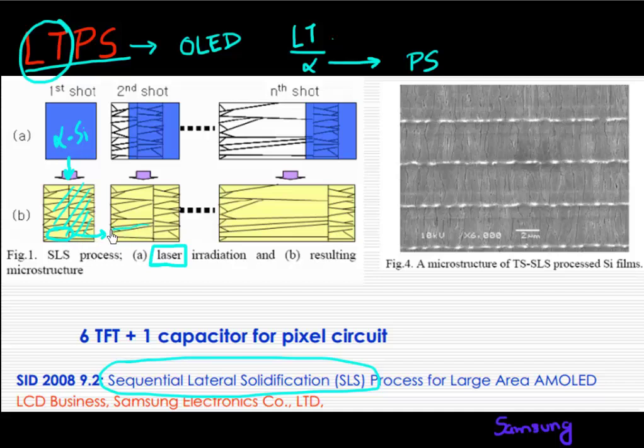And some of these grains merge and you get a larger grain. And then you fire it up with a laser again. And these grains start to become even bigger. And each time you make the grain bigger, that improves your mobility in this polysilicon material.